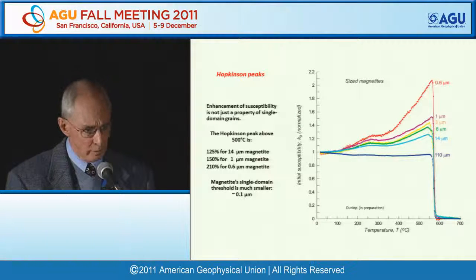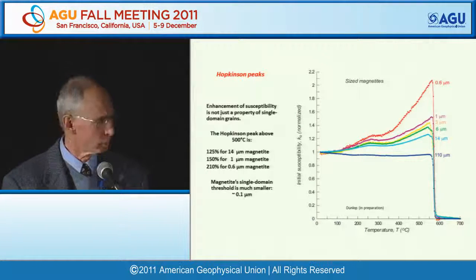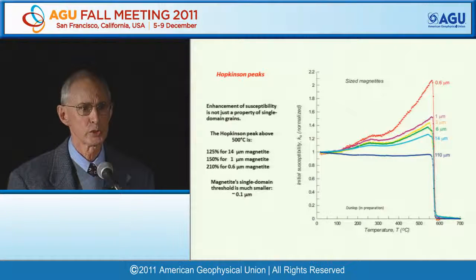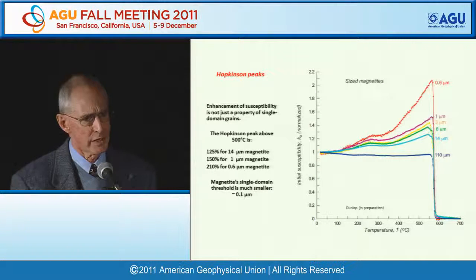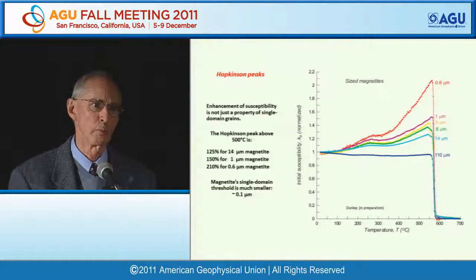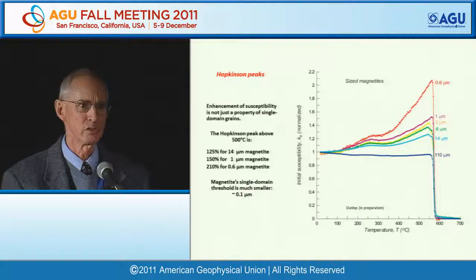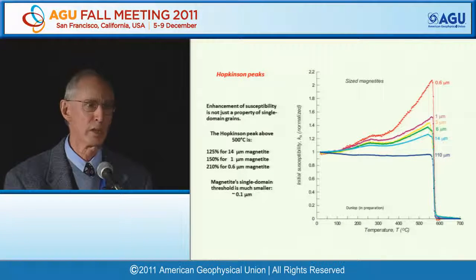They look very similar. Not identical, but very similar. They're close to reversible. Of course, as the grain size gets smaller, you can't really control the atmosphere in the Bartington bridge that was used to get these data. So there is some oxidation of the magnetite, so that the peak height does drop somewhat for the smaller grains. The shape of the curve, however, does not change.